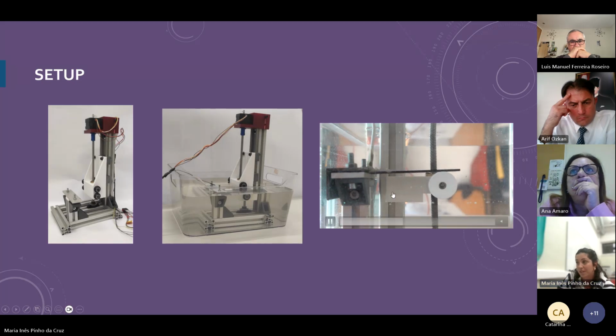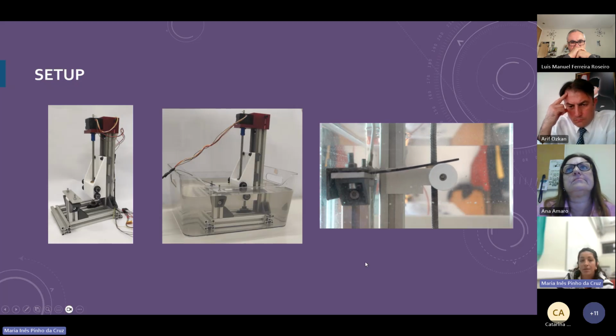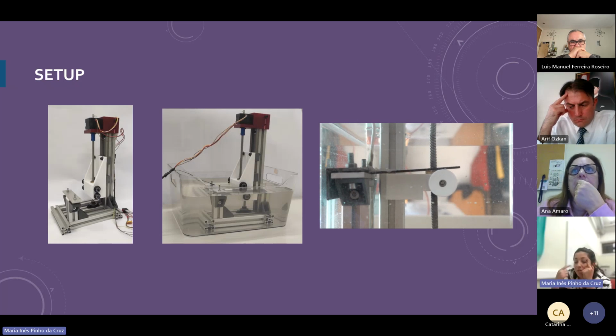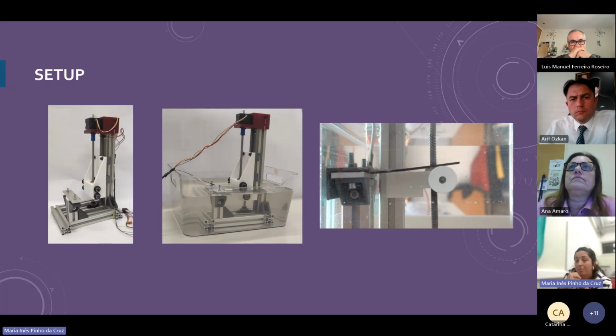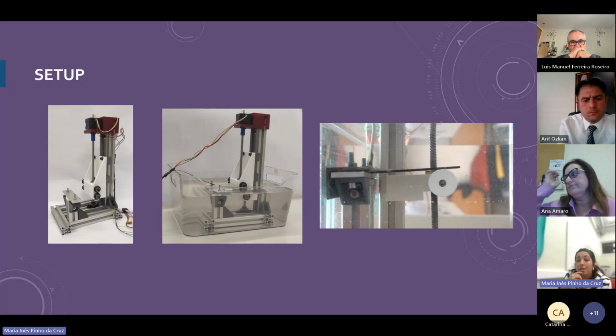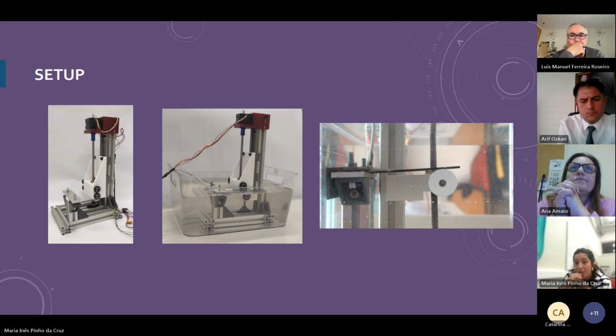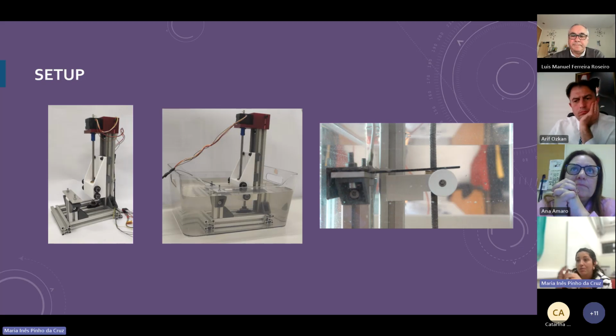Here is how we make the tests. In this video, we'll see that we have displacement up and down. For the tests, the speed rotation of the motor is 5 RPM. We have approximately 35 cycles of loading and unloading. After the tests, we invert the samples and we try to make a pause of 10 minutes between tests to eliminate residual stress and establish baseline conditions for the next steps.